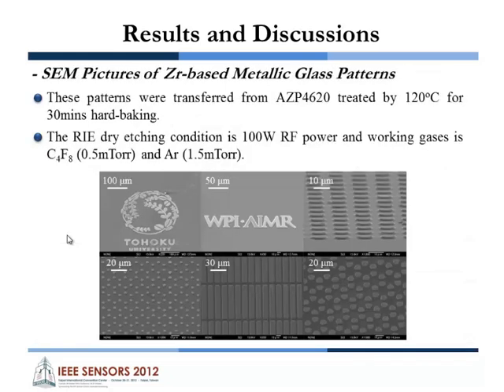On this page, I show some SEM pictures, and we can see we define metallic glass thin film patterns, transferred from the photoresist, from millimeter scale to micrometer scale here. This is metallic glass and this is the silicon substrate. After the RIE dry etching, we also need to confirm the amorphous structure, so we use TEM to confirm it. It is an amorphous structure.